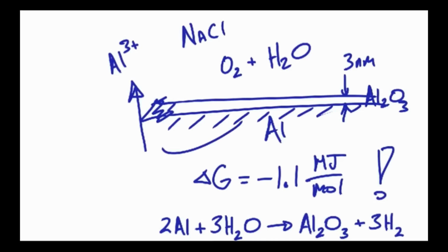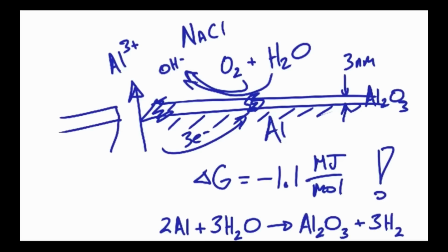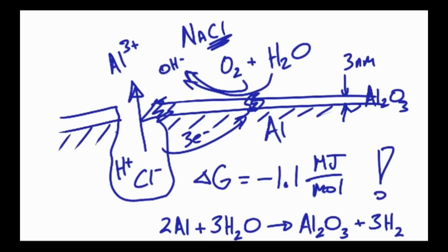The aluminum loses those 3 electrons. The 3 electrons go off someplace else, finding another defect so they can pass through the film, and they combine with the water and the oxygen to form hydroxyls. The aluminum, meanwhile, reacts with water to form aluminum oxide, and it also forms H+. These H+ ions collect in an occluded cell and attract the chlorides, the sodium chloride, and we form a dilute hydrochloric acid, which continues dissolving away the aluminum metal.